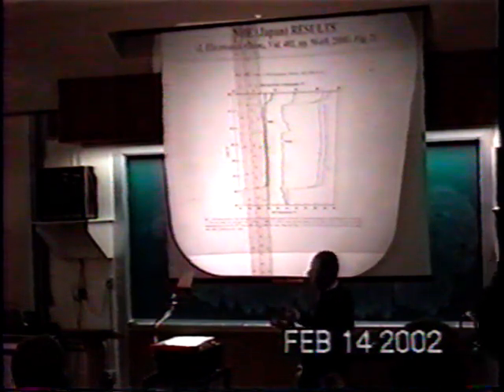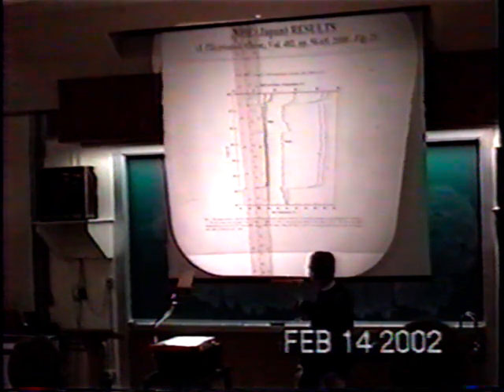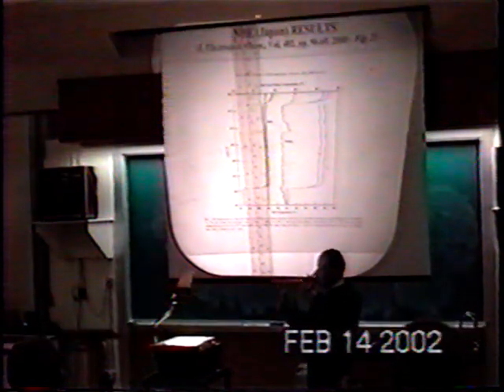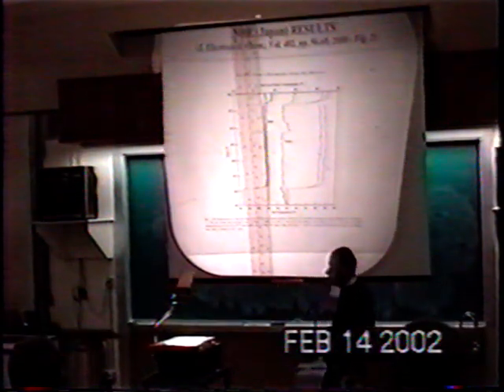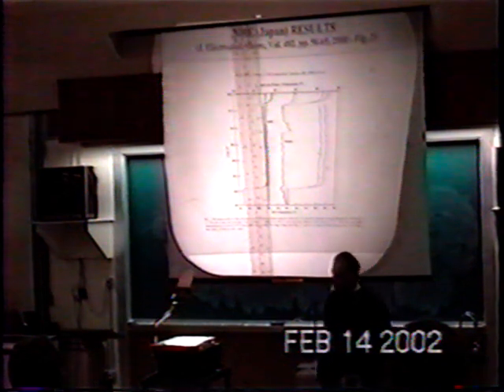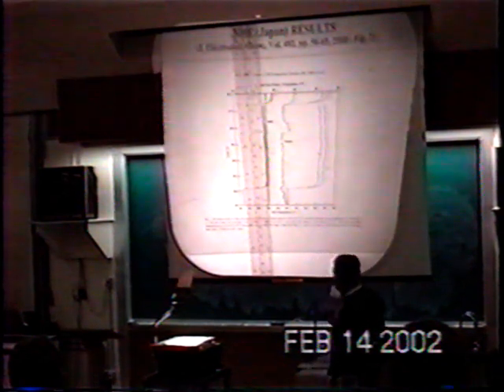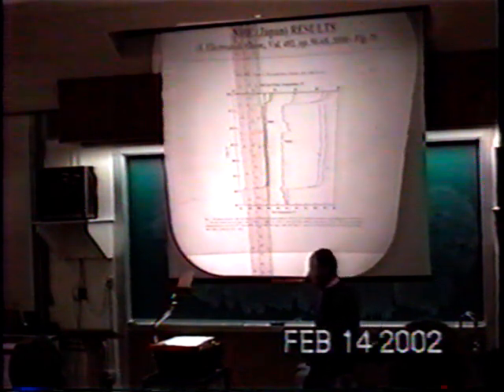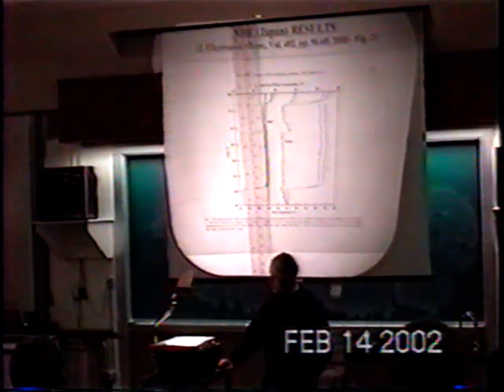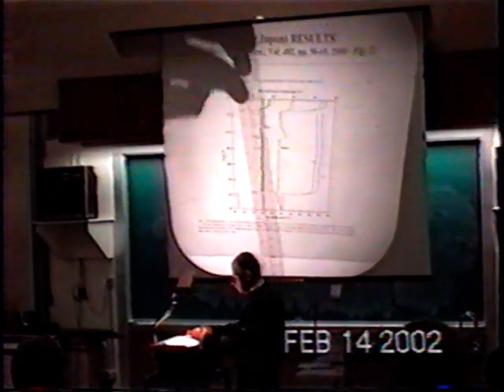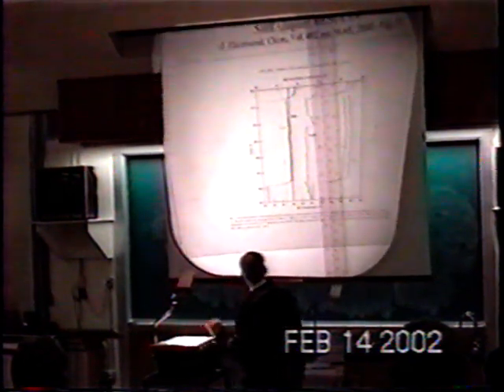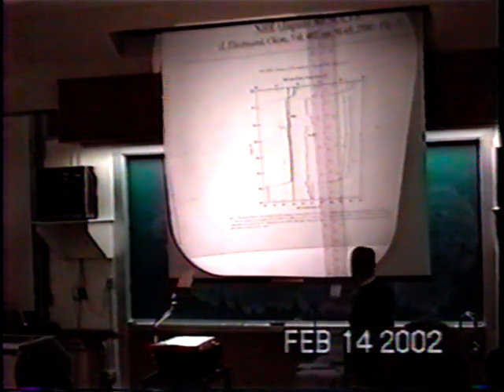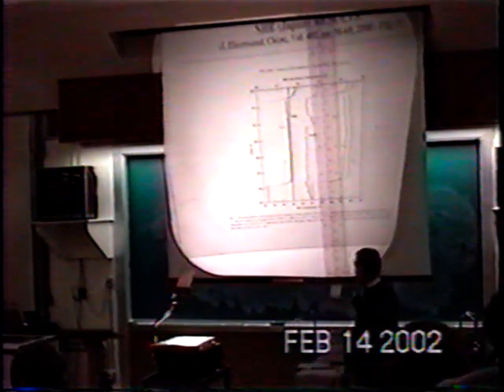This is a chart feeding out from the chart recorder, and so this is time going along this way. And so this is actually how you sort of look at the chart paper right in front of you. That's a little different way to do the scale. So this is a scan of the actual experimental data. And the temperature for that cell goes down with time exactly as you predict. The power is going down with time, the temperature goes down with time. The other cell, we'd expect it to go down with about the same slope, something like that, but it doesn't. The temperature actually goes up with time. Even though the power is going down, the temperature is going up.